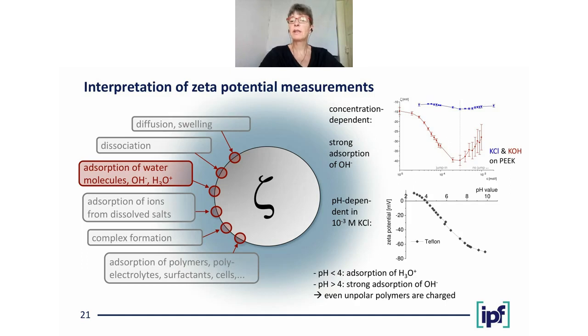And that is the reason that an intrinsically uncharged and unpolar polymer like Teflon does have a pronounced Zeta potential. Its isoelectric point is around pH 4 because of the very strong adsorption of the hydroxide ions above pH 4 that lead to a strong negative Zeta potential.